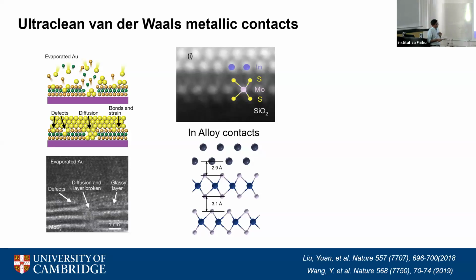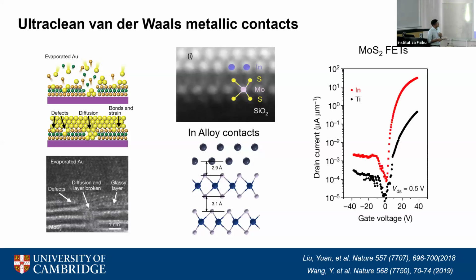They also looked at the sulfur which is very close to the metal, and that had a very similar interaction. So there was no evidence of chemical interaction between the metal and the sulfur. It was more of a van der Waals-like interaction, like you would expect between individual layers in the 2D material, and that is why we call them van der Waals contacts. There's a van der Waals gap between the metal atom and the semiconductor of around 3 angstrom, and this helps us avoid any diffusion or defects at the interface.